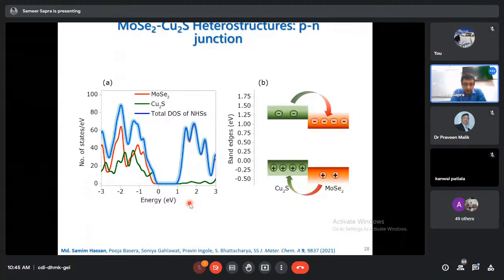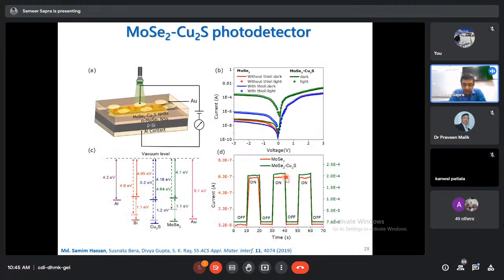What they tell us is the kind of heterostructure that you've made. Just focus on the partial density of states over here. The red one is molybdenum selenide, which does not have any density of states at the top of the valence band, but the bottom of the conduction band is made up of molybdenum selenide, whereas the top of the valence band is essentially cuprous sulfide. Schematically, I would show it like this, as a type 2 semiconductor heterojunction, where the electrons are pushed over to molybdenum selenide and the holes are taken up by cuprous sulfide. That's a natural charge separation that is happening over there, right? And if that is the case, one tends to make some devices out of it.